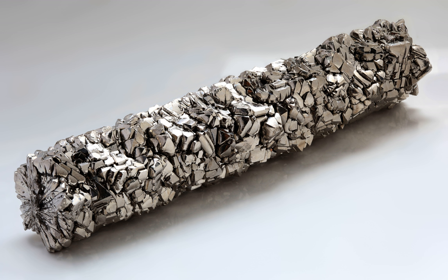Production and fabrication. The processing of titanium metal occurs in four major steps: reduction of titanium ore into sponge, a porous form; melting of sponge, or sponge plus a master alloy, to form an ingot; primary fabrication, where an ingot is converted into general mill products such as billet, bar, plate, sheet, strip, and tube; and secondary fabrication of finished shapes from mill products.